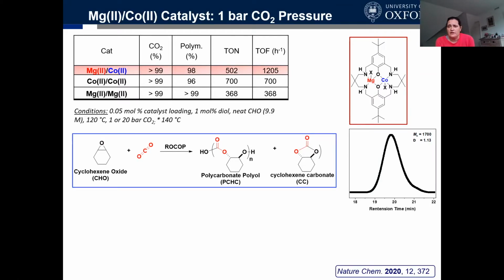The other point to note is that we're making polyols. You see the GPC trace in black. We have a low molecular weight, which is exactly what you want for this type of product, and a very narrow dispersity of molecular weight, a Gaussian distribution. And that is, as I say, important when we use those polyols to make further products.